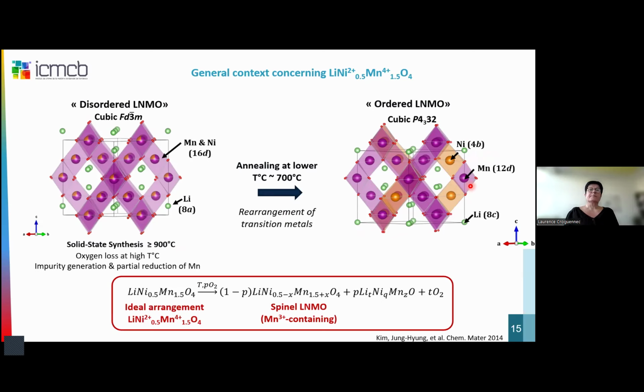So in fact, I would say the phase equilibrium when we are doing the synthesis of the spinel oxides can be really described by these equations here. We are really always in balance between an ideal stoichiometric phase with only nickel 2 plus and manganese 4 plus, and a phase deficient in nickel that does contain manganese 3 plus for charge compensation, and impurities rich in nickel, with, of course, an evolution of oxygen.